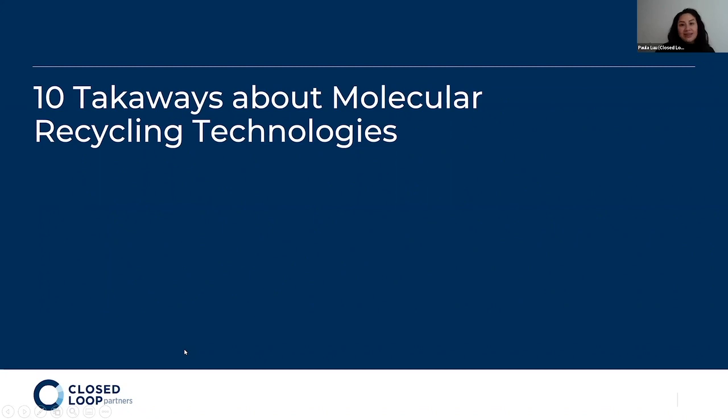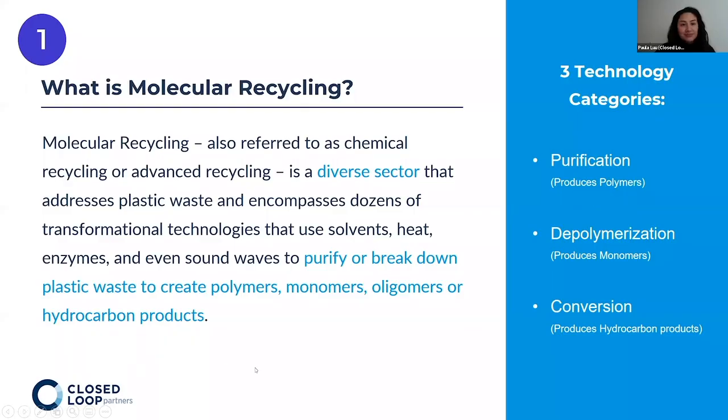So for today's talk, it's a quick one, but I wanted to walk you through 10 takeaways from our research in this field over the last 4 years. So what is molecular recycling? It's not a monolith. It's really a diverse set of technologies that are leveraging either solvents or heat or enzymes, even sound waves to purify and break down different kinds of plastic waste. There are 3 types of technologies within the sector: purification, which produces polymers; depolymerization, which produces monomers; and conversion technologies, which produce hydrocarbon products like naphtha or diesel or paraffin waxes.